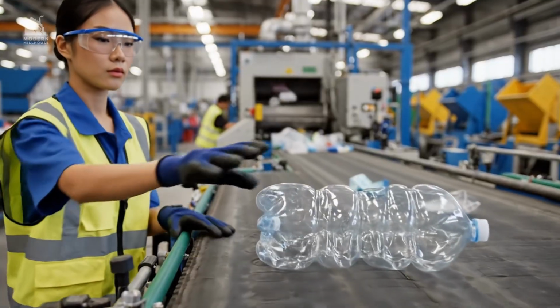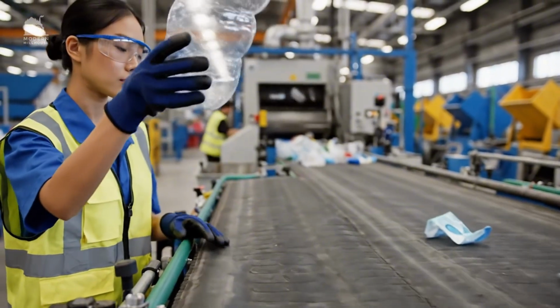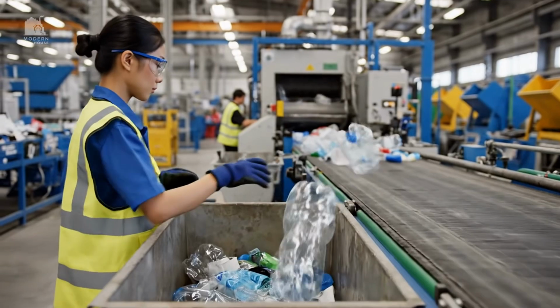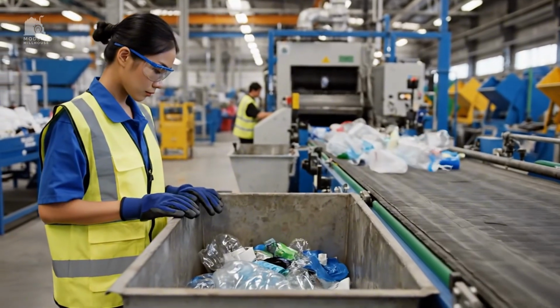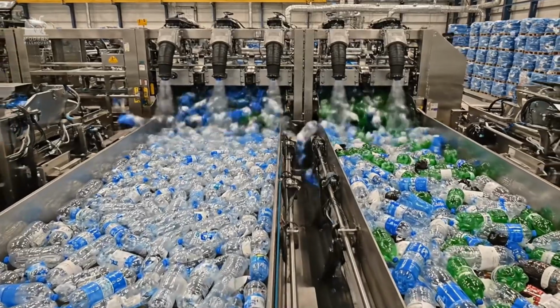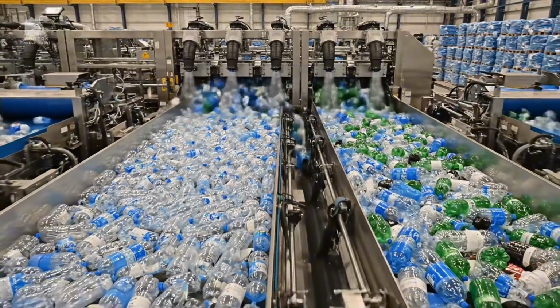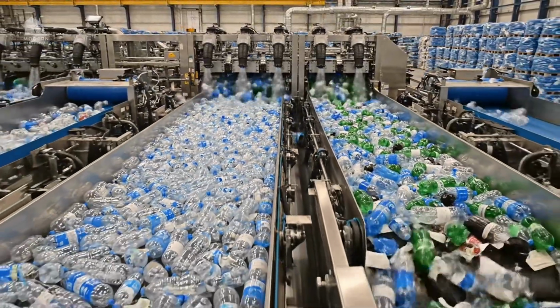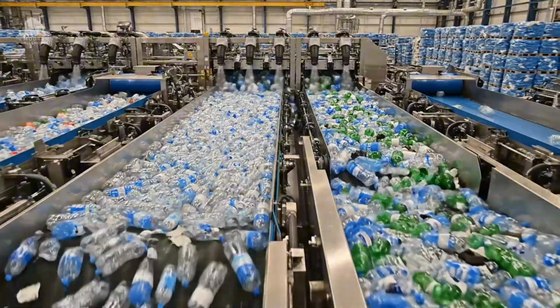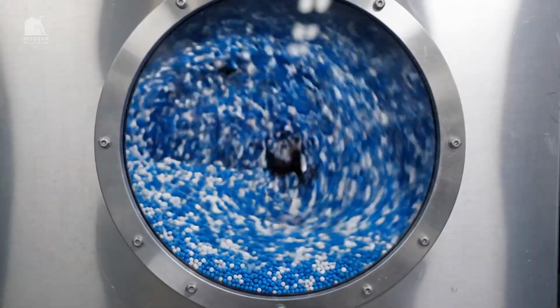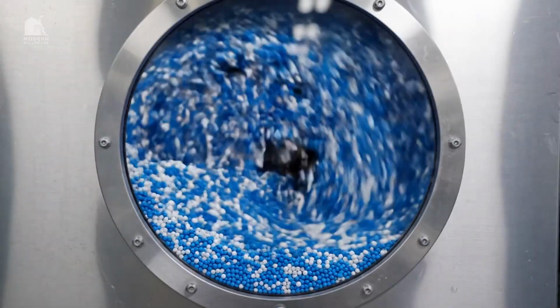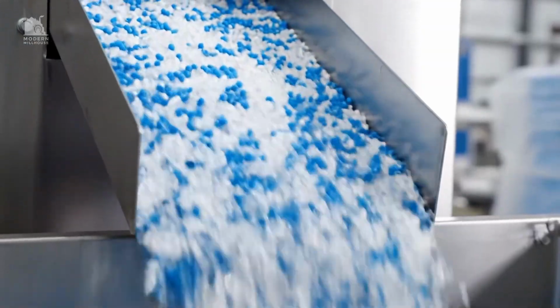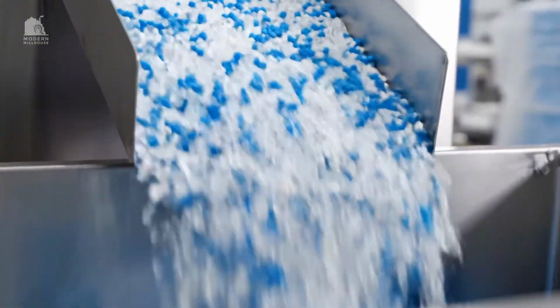PVC is especially dangerous. A small amount can degrade during processing and create defects that show up as weak spots in fiber. Color matters too. Clear PET typically makes higher value fiber, while mixed colors limit what the recycled material can become. Moisture control is non-negotiable. Dry PET processes cleanly. Wet PET degrades and loses strength.